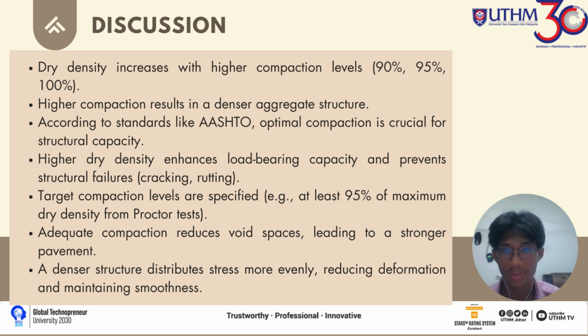As for discussion, dry density increases with higher compaction levels. Higher compaction results in a denser aggregate structure according to standards like AASHTO. Optimal compaction is crucial for structural capacity. Higher dry density enhances load-bearing capacity and prevents structural failures such as cracking and rutting. Target compaction levels are specified, such as at least 95% of maximum dry density from proctor tests. Adequate compaction reduces void spaces, leading to a stronger pavement whereas the structure distributes stress more evenly, reducing deformation and maintaining smoothness.